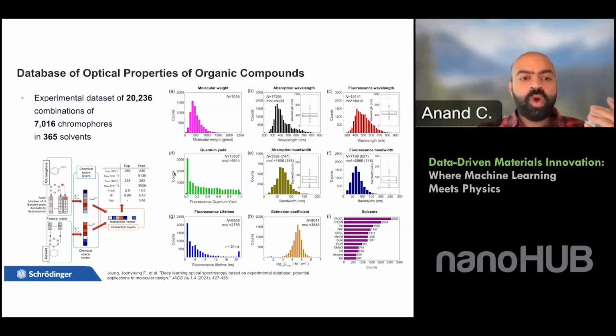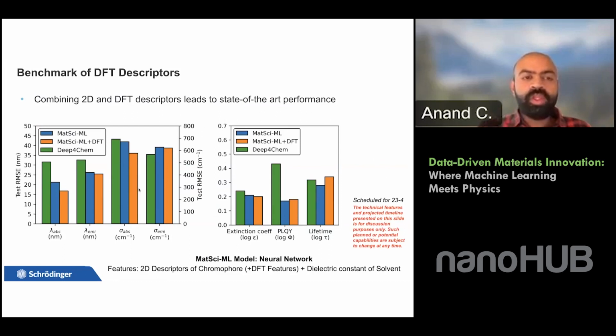So the approach that we took was slightly different. We generated the 2D descriptors and DFT descriptors for the chromophore, and we concatenated them with the 2D descriptors of the solvent, and we provided those combined descriptors to the machine learning model. And we provided them to a list of machine learning models like multi-layer perceptron, XGBoost, random forest, etc. And we automatically select the best performing model for a particular property.